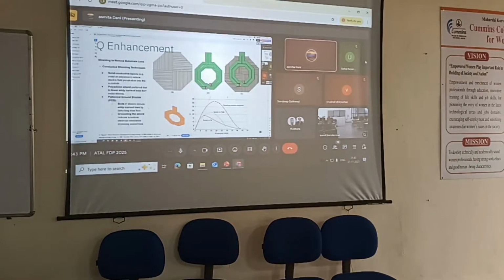Then here an example is shown with a patterned ground shield. So we see that the spiral on a patterned ground shield versus silicon has much larger Q. Because that helps in breaking up the eddy currents that are forming in the substrate, so that improves the Q factor as well.